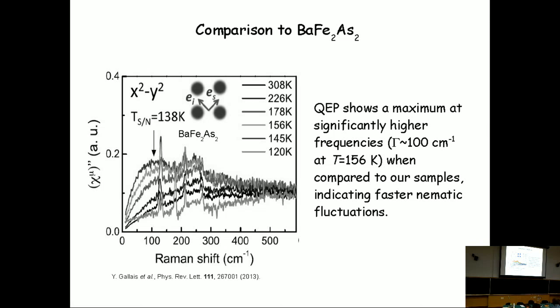Since you are interested in separating these two effects, why not pick a material like, say, sodium 111? They differ by a lot, right? Why not pick another material? Yeah, sure. Sodium 111, they differ by more than just 10 Kelvin, a lot, right? Or you can go to lithium 111 or iron selenide, where the magnetic order disappears. Then you can really see what's going on.